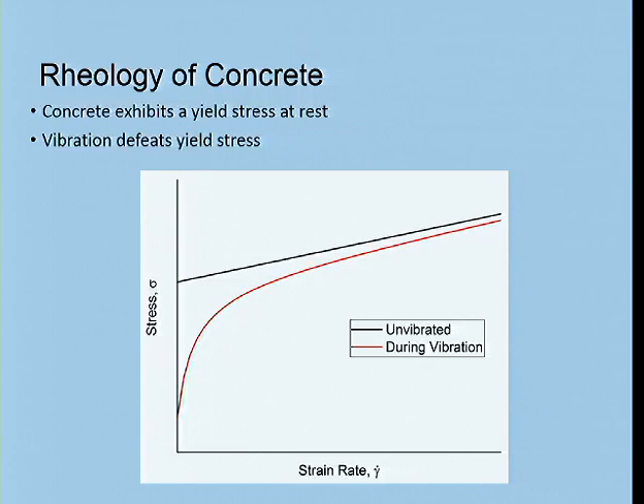When we are vibrating the material, the behavior is different. So we can do these kinds of rheological tests under vibration, and we get a different story. And the story basically is that near where we expect to have yield stress, that yield stress is defeated, and we actually have what is essentially like a Newtonian fluid when we're under vibration. Why is this important? Because vibration is going to be how we consolidate the material, and it's the period of time that is of concern today, when air bubbles are moving and rising through the material.